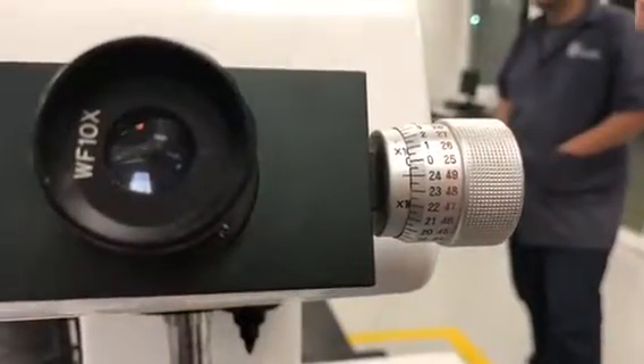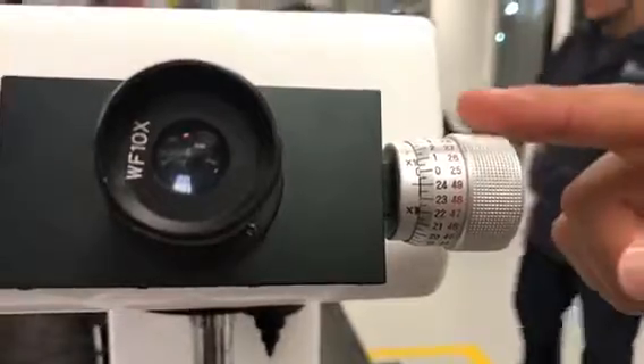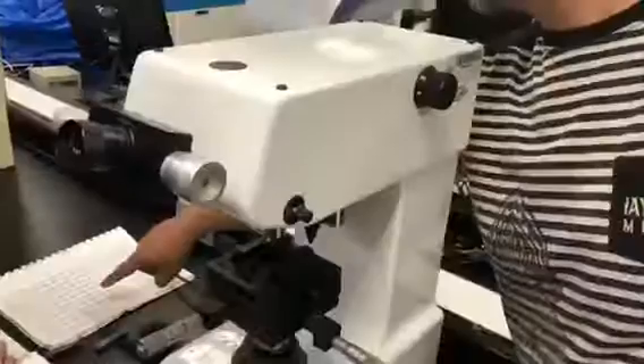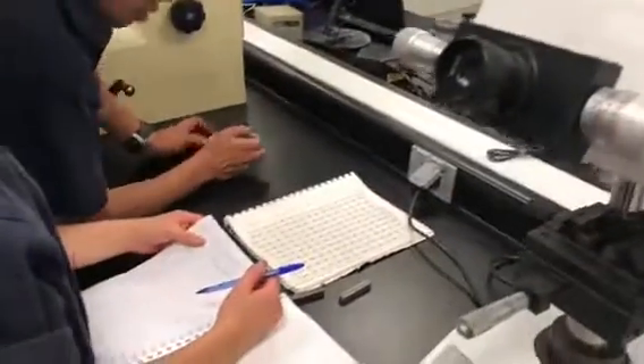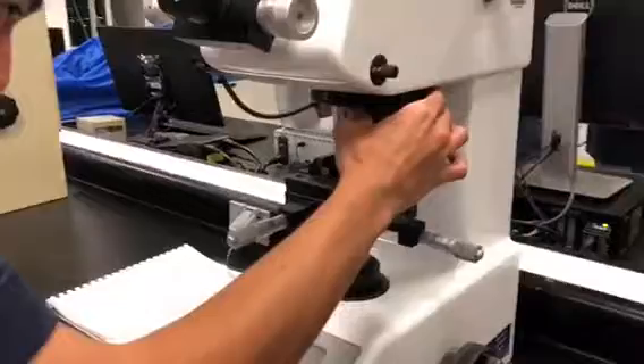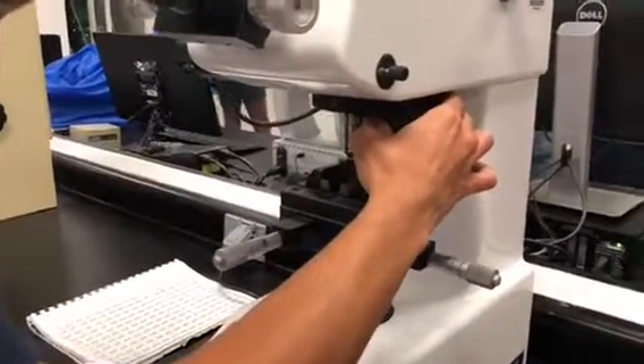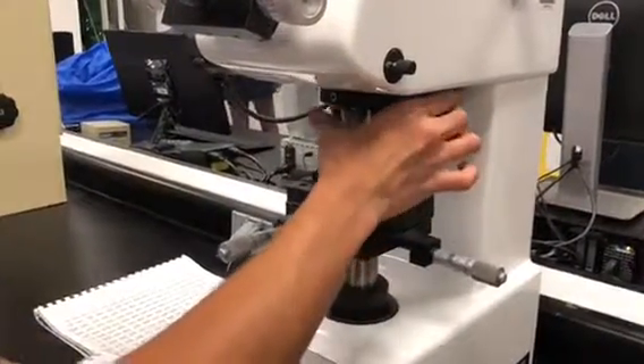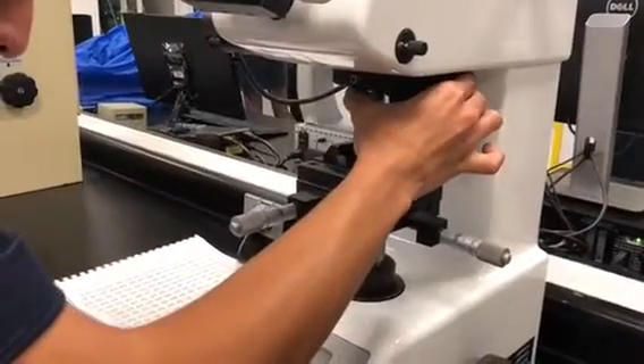The manual Vickers test involves the use of the microscope for the indentations measurement and the mechanical activation of the machine. The 300 grams applied load is applied during 15 seconds in the same way in which the automatic setting was applied, and the extremes of the generated diamond shapes are measured through the microscope.